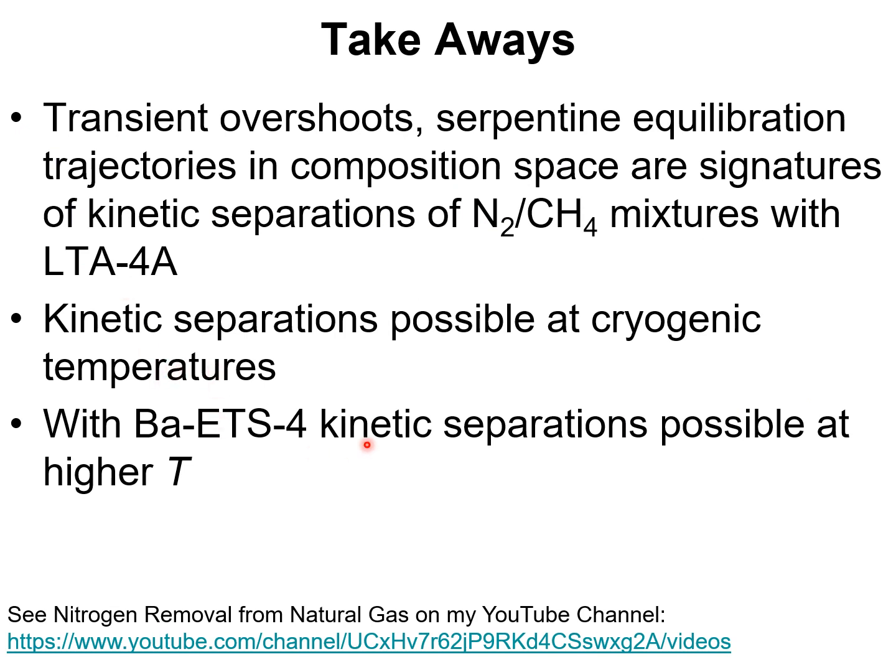Let us summarize what we have learned from our analysis of nitrogen methane mixture separations in LTA 4A zeolite. On the basis of the analysis of the Habgood experiments, we have established that transient overshoots and serpentine equilibration trajectories in composition space are signatures of kinetic separations of nitrogen methane mixtures in 4A zeolite.